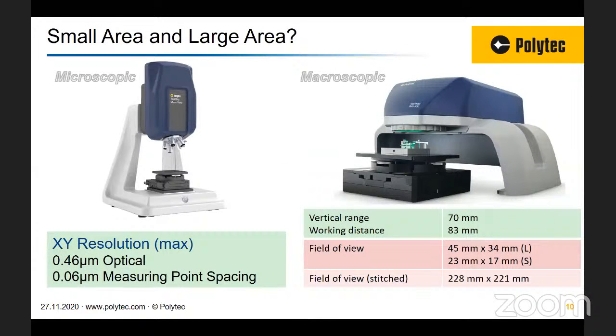I always like to talk about how big and how small. For how small, you start with the microscopic type system, and for how big, the macroscopic type system. A microscope makes small things look big, and the optical performance starts from 0.46 microns, and the point-to-point spacing, because the digital sampling rates are much higher, starts from 0.06 microns. Whereas a macroscopic system makes larger things look big. We have a very interesting vertical measurement range: it's possible to measure a 70mm step without crashing into the artifact. The macroscope has a standoff distance of 83mm, and within a single measurement you can get up to 45mm. With stitching, you can go far beyond that.